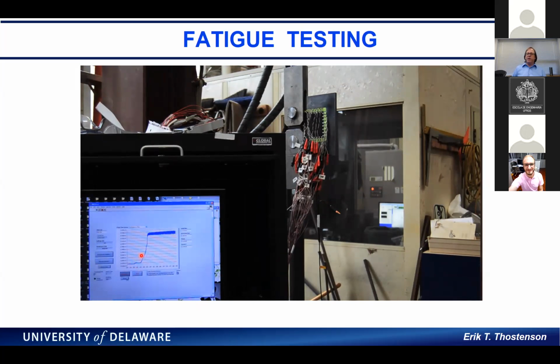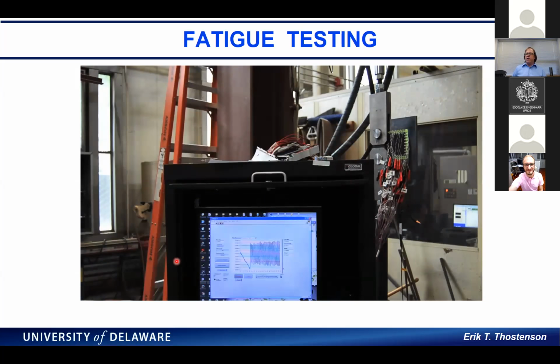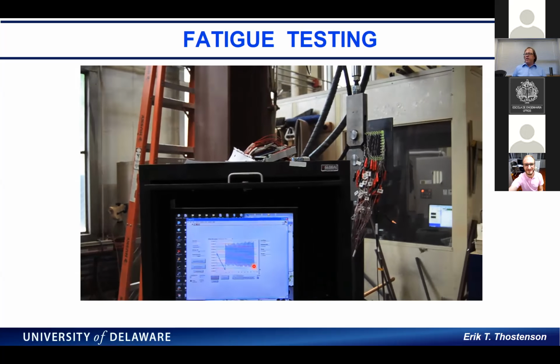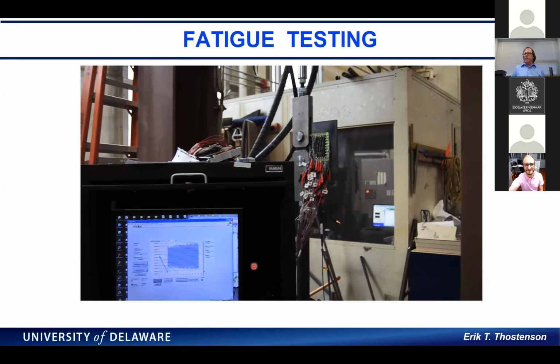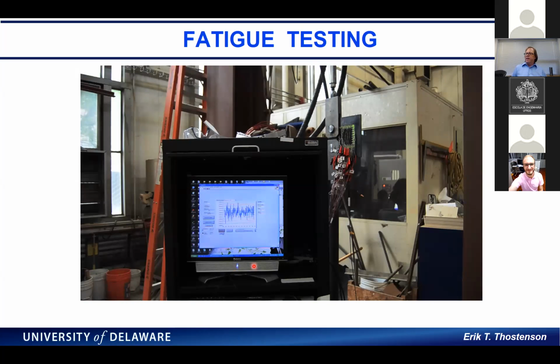But you can see on the computer screen that as we start loading the specimen, the electrical response is in real time with the specimen. The specimen in the background is a compact tension specimen, and you see that initial loading, and then we can measure the cyclic loading.